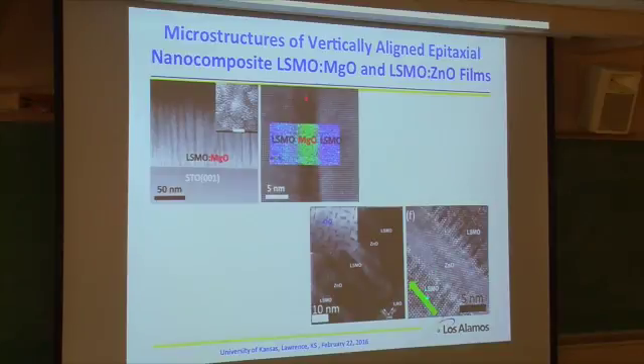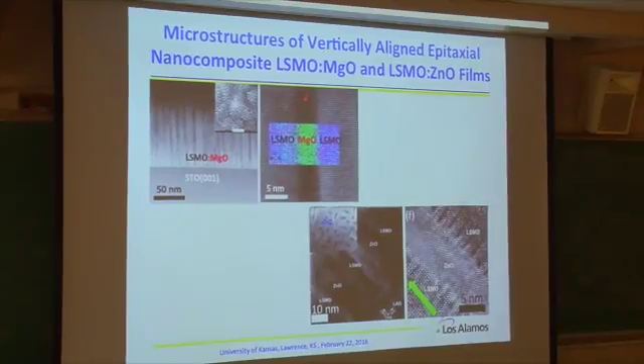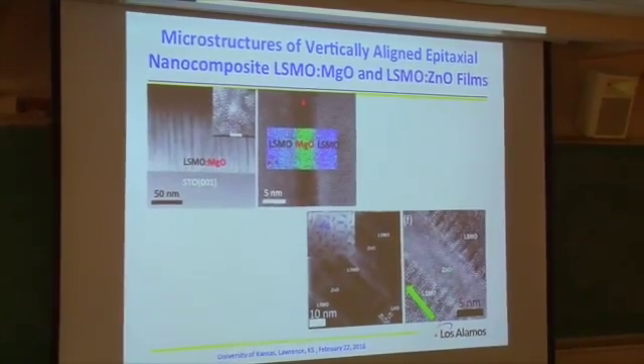We haven't published that yet. Actually, since this is magnetic material, you have this magnetostrictive effect. When you apply a magnetic field, you can tune this property of the zinc oxide. The reason is, since they are attached together, coupled, they will change the band gap of zinc oxide. Actually, you can tune the optical property of the zinc oxide. You can do it that way as well.